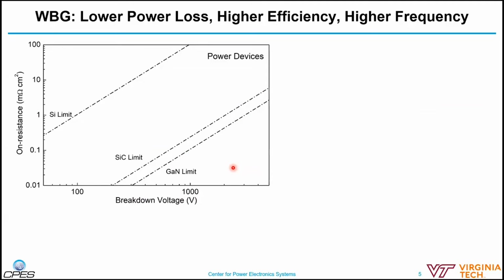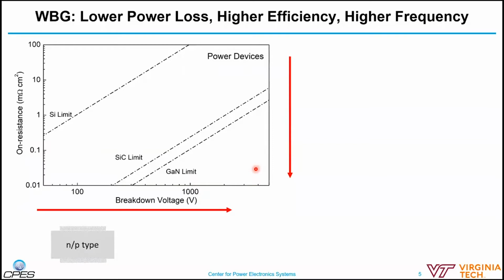In power devices, we usually prefer the device to have as small an on resistance as possible, such that when conducting a specific current, the conduction loss will be low. At the same time, we want the device to be able to block high voltage. So if we plot the on resistance as a function of breakdown voltage, we prefer devices towards the right bottom corner. However, there is a fundamental trade-off between the on resistance and the breakdown voltage. This is not very difficult to understand if we think about a thin semiconductor layer. If we want to achieve a high breakdown voltage, we want a lower doping concentration and to make this layer as thick as possible, and that will certainly increase the on resistance.